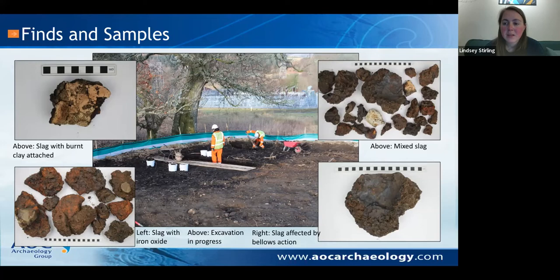But you can also see in the top left picture a piece of slag that has burnt clay still attached to it. This is where the slag has formed up against the structure of the furnace itself. So this is a really good indication of what sort of materials they were using to build these furnaces. Even though we don't have much evidence of the furnace itself, the team should hopefully be able to get some good insights into that.